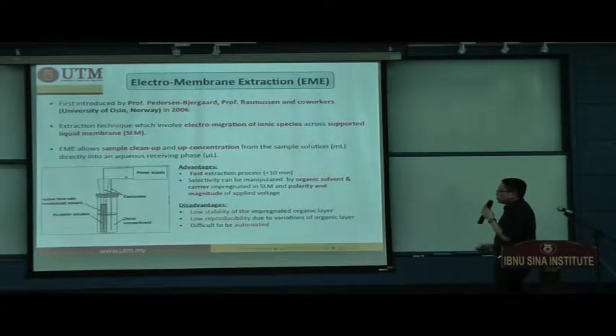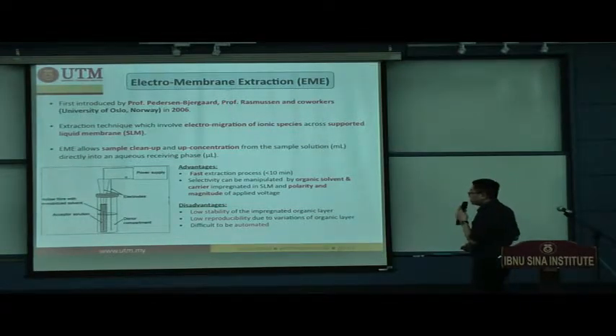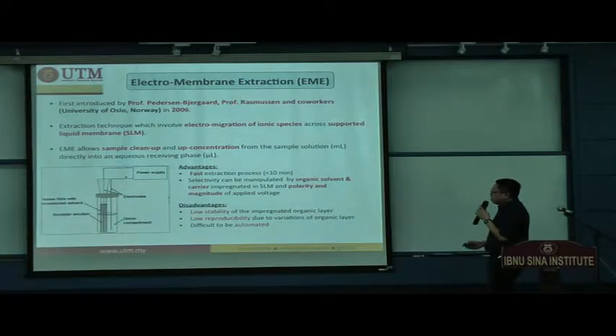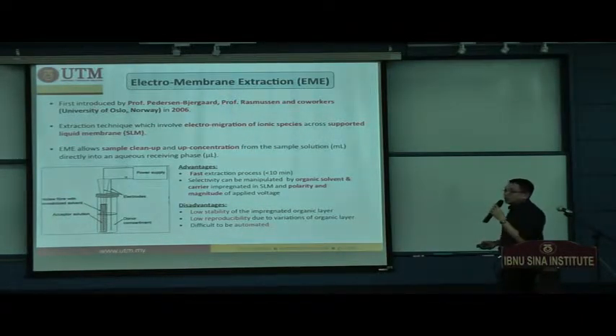But there are also several disadvantages of this technique. For example, low stability of the impregnated organic layer under high agitation conditions and also in high electric field environments. Low reproducibility due to variation of the organic layer. This is because when you use this method, you basically prepare a new hollow fiber membrane with the organic layer for each analysis. So the layer of organic solvent is really crucial in determining the mechanism. And thirdly, this method is very difficult to automate, and therefore very difficult to commercialize.